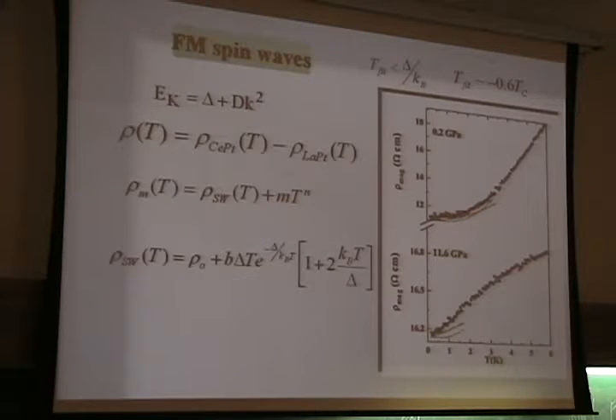So on the magnetic side, we analyze this material using the spin wave scenario for an anisotropic ferromagnet, where the dispersion relation for the magnons is given by this. Okay, we also subtract the lanthanum contribution, the phonon contribution of this system. Okay, and in this scenario of spin waves, you have the resistivity given by this kind of formula. Okay, and here we show for two examples, for low pressure and high pressure, how these two terms of the resistivity behave. Okay, you have what we call the spin wave contribution, and what is called the electron-electron contribution. Okay, that's given by this formula here.